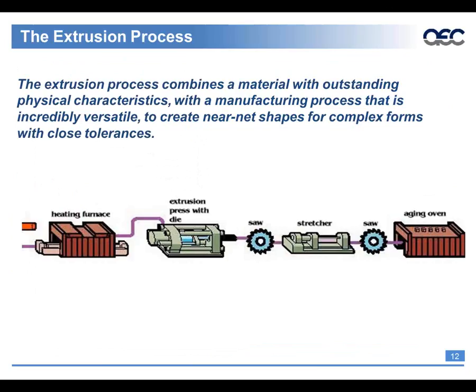This shows a little bit more detail about the first two slides that we showed regarding the basics. Basically aluminum is heated in the furnace to a malleable temperature, anywhere from 750 to 900 degrees. It's inserted into the extrusion press with the die on the end. It's pushed with a huge hydraulic ram. It could be pushed out anywhere between 100 and 300 feet.